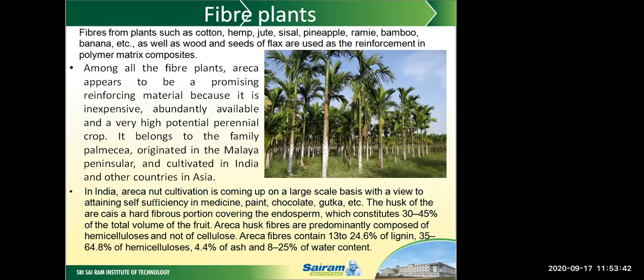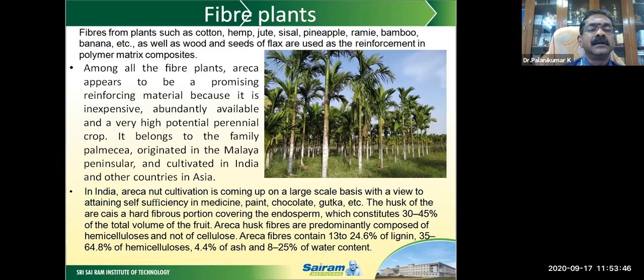So these materials are used for manufacturing and making of paint, chocolate, gutka, etc. The husk of the areca is a hard fibrous portion covering the endosperm, which constitutes 30 to 45% of the total volume of the fruit. Areca husk fibers are predominantly composed of hemicelluloses and not of cellulose. Areca fibers contain 13 to 24.6% of lignin, 35 to 64.8% of hemicelluloses, 4.4% of ash, and 8 to 25% of water content.